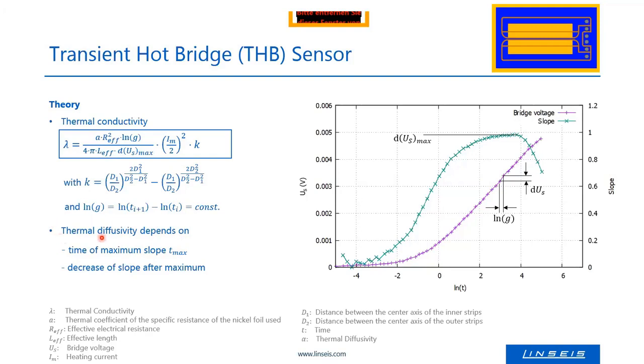We can also calculate the thermal diffusivity. This diffusivity is calculated at the end of the measurement, when the maximum here is reached, and then you can see that the first derivative goes down here. This means the slope is getting smaller. From the time it takes until the linear, more or less constant slope is left and we go into a transition to a steady state, from this time somewhere here, we can calculate the thermal diffusivity.